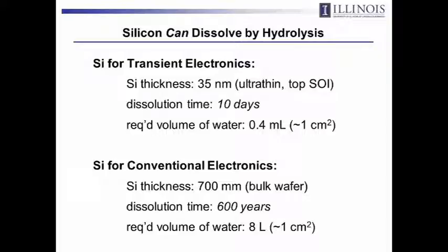Now, if you compare that to the kind of silicon electronics you find in your laptop or your cell phone, you see some notable differences. The silicon thickness in that case may be 700 microns, not millimeters, microns. If you extrapolate these rates to that thickness, then the dissolution time is 600 years, and you need a lot of water to do that. So a conventional silicon wafer platform is not transient in any way that we would consider it to be. And so thin silicon is critically important.